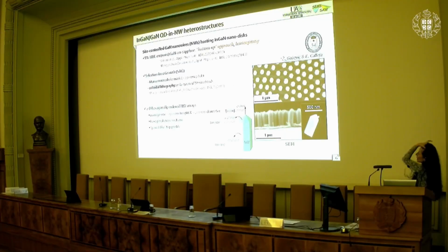So the III-nitride nanowire heterostructures that we used, as I mentioned, were grown by our colleagues at a different university in Madrid. This was done by plasma-assisted molecular beam homoepitaxy using a selective area growth technique that was achieved by colloidal lithography. As you can see in this scanning electron microscopy image here, these nanowires exhibit a hexagonal cross-section with lateral facets defined by the non-polar M planes.